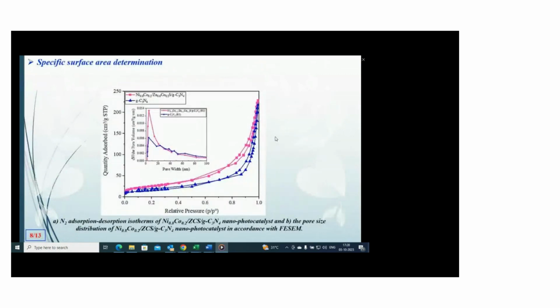This figure shows the nitrogen adsorption-desorption isotherm of g-C3N4 and ternary photocatalyst aligned with the corresponding pore size distribution shown in the inset. According to the figure, both isotherms exhibited characteristics of type 4 isotherm. This indicates the presence of mesopores in the structure, and additionally, the isotherms demonstrate a sharp increase in adsorption at high relative pressure, indicating the presence of large mesopores and macropores.